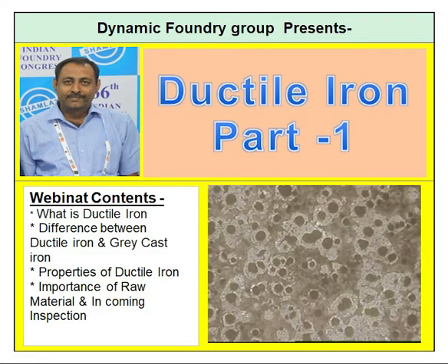This is a microstructure of fully ferritic iron. You can see a fully ferritic structure here. Second is where the matrix is ferritic pearlitic, where ferrite may be available or pearlite may be available. It may be 40-60 or 60-40. It's a combination of ferrite and pearlite together. So that is around 500/7 grade, we can say, the ferritic pearlitic grade, where 40-60 or 60-40 proportion is available. The hardness range required here is 180 to 230.